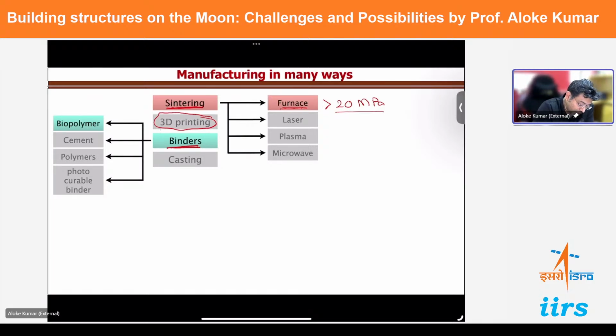We have also done 3D printing, which still gives slightly weaker bricks, but it's good enough. We have used different types of binders. So we realized, after we used guar gum, that you don't have to use just bacteria. You can also use biological polymers, and that's giving very good results. So we've recently used biopolymers to construct bricks, and we have gone one more step further.